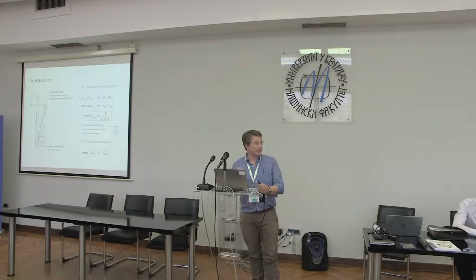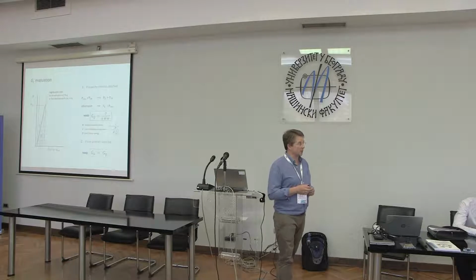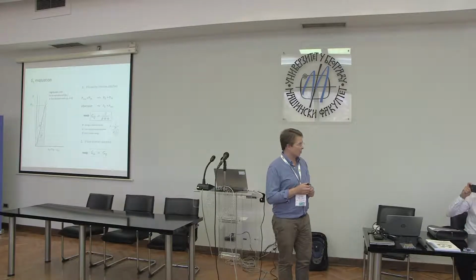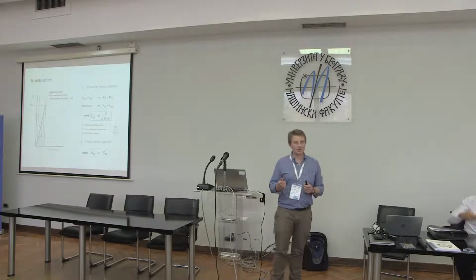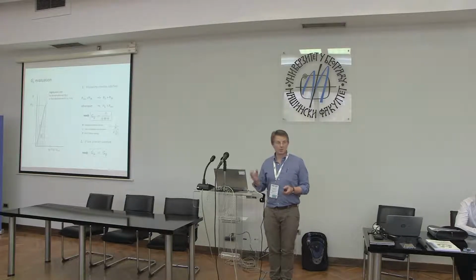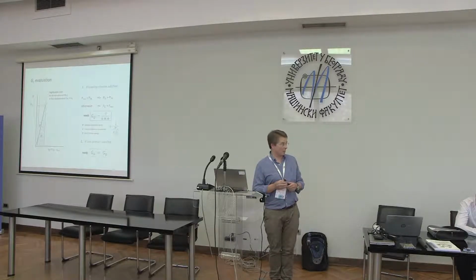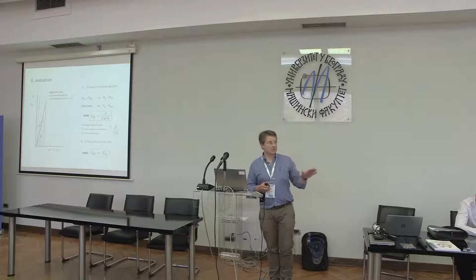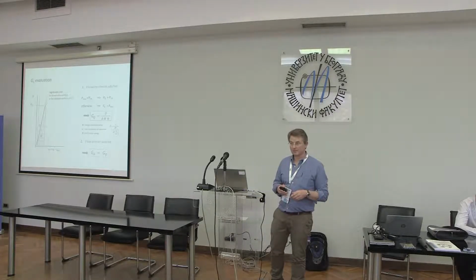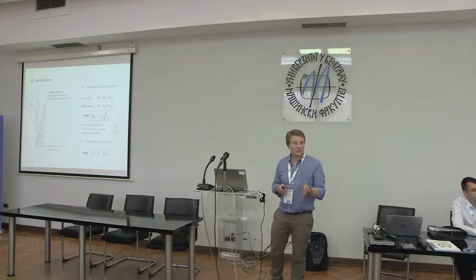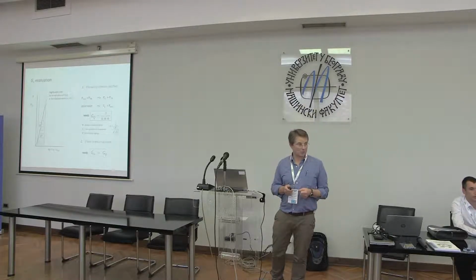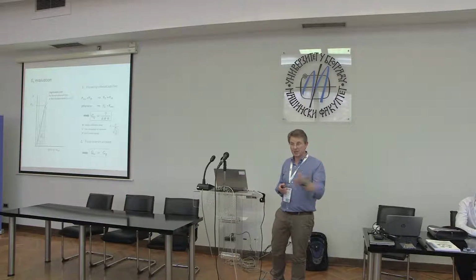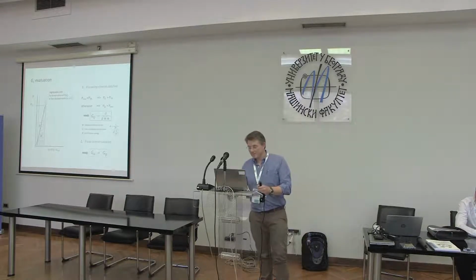The main complication for us has been the initial condition. So if you're performing these experiments, we would advise you to look carefully at the initial crack that you're putting in. Of course, everything is very, very sensitive to that initial crack. All you're measuring is this 5% offset value of force displacement, and that's critically dependent upon the initial condition.